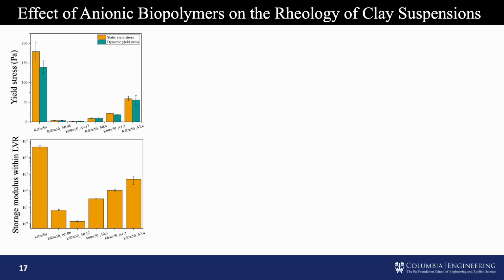Let's see how these anionic biopolymers, the negatively charged non-binding biopolymers, affect the rheology of the clay-based systems. We're discussing the yield stress and storage modulus. From left to right, we are increasing the polymer concentration, and the first group, K60W50, is just pure clay. K means kaolin, W means water, and 60-50 means the clay to water ratio. We can see that both storage modulus and yield stress show two trends. If you add a very small amount of polymer, it immediately reduces yield stress by more than 2 orders of magnitude. Same for the storage modulus. And then if you keep increasing the polymer concentration, it eventually increases the modulus and increases the yield stress again. So let's see what is happening in each stage.